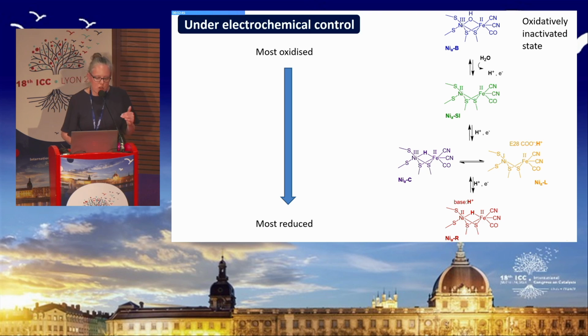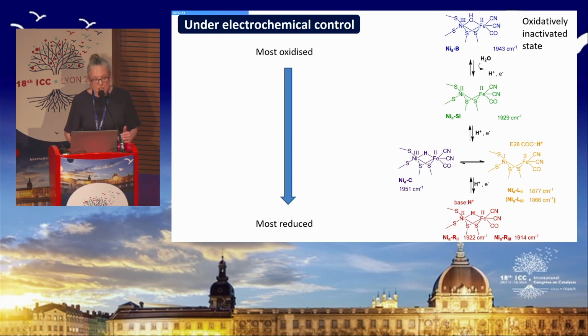There is also a further oxidized state of the active site, which is not within the catalytic cycle, but can be generated under conditions of oxidative stress in physiologically relevant conditions, and generated by oxidation or by reaction with oxygen in the enzyme when it's isolated from the cells. So as I mentioned, each of these states of the active site has a characteristic CO vibrational band position, and we can then use those to determine which active site states we have present under any particular set of conditions.